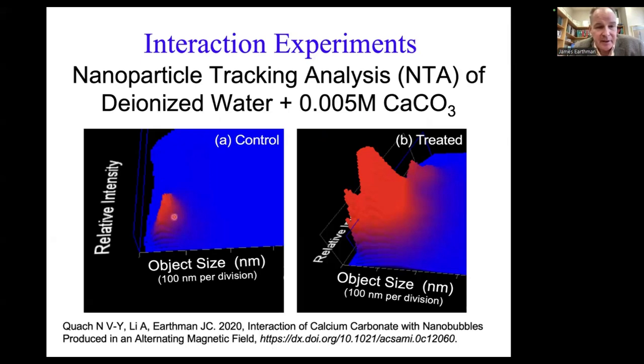And we get one peak in relative intensity. We get one peak in object size, what you'd expect with just calcium carbonate. When we put the nanobubbles in, same water, we get three peaks. We get a high peak, which is apparently the nanoparticles because they have higher index of refraction. They should scatter light more.